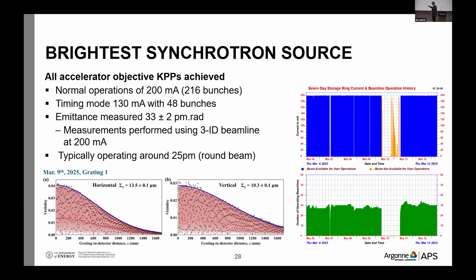So this is the measurement in the horizontal plane and in the vertical plane using this grating that I quickly described. And you can see that the horizontal beam size, so this is the photon beam size this time, not the electron beam size, is about 13 micron and 10 micron in the vertical direction. In the old machine, the horizontal beam size was about 280 microns.